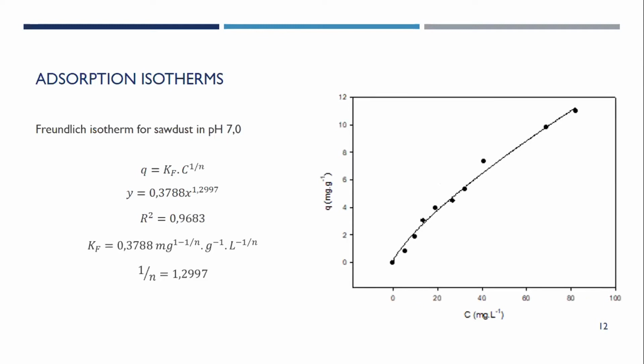The Freundlich isotherm for Sawdust at pH 7, which was constructed following the same equation, showed the Freundlich constant to be 0.3788, while the exponent 1 over n was shown to be 1.2997. In comparison, we can see that the Freundlich constant, which determines the rate of adsorption, is much higher for Chitosan than for sawdust at the same pH value.